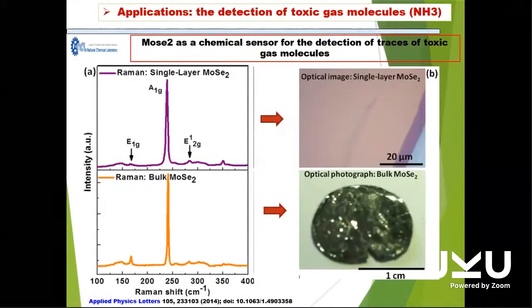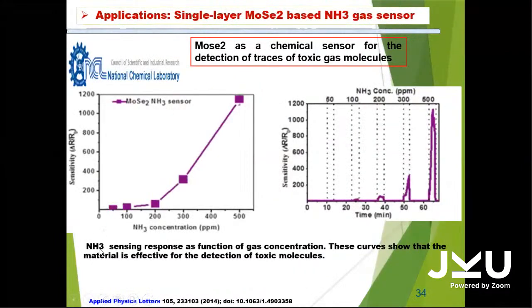The third type of application is that we use this material for toxic gas molecule detection. And the sensing response as a function of gas concentration on this curve shows that it's possible to use this material for the detection of the toxic gas molecule. You can see here.